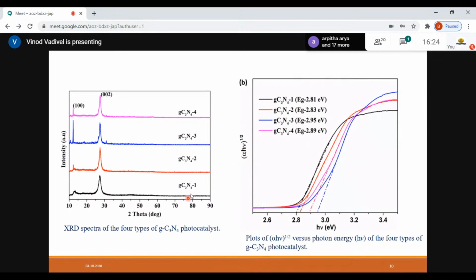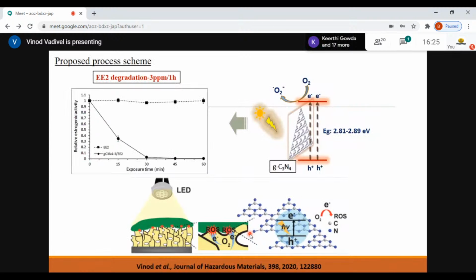We saw that GC3N4 1 is the bulk GC3N4, without hydrothermal treatment. 2, 3, 4 are treated with hydrothermal: GC3N4 2 is with DI water alone, 3 is with ammonium hydroxide, and 4 is with acetic acid. So when we change the precursor with respect to hydrothermal treatment, you can see the crystallinity of the material enhances. Here we saw that GC3N4-3 was the best one, and the band gap supported the PXRD data, providing 2.95 electron volts. When we studied the visible process, the experimental conditions, we found the ammonium hydroxide based GC3N4 was giving the best results.